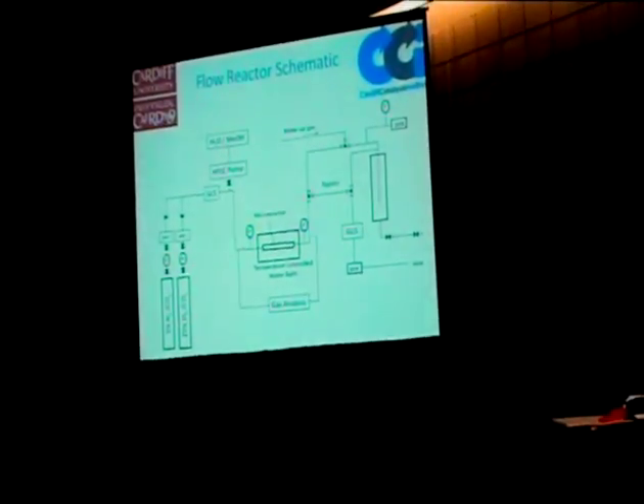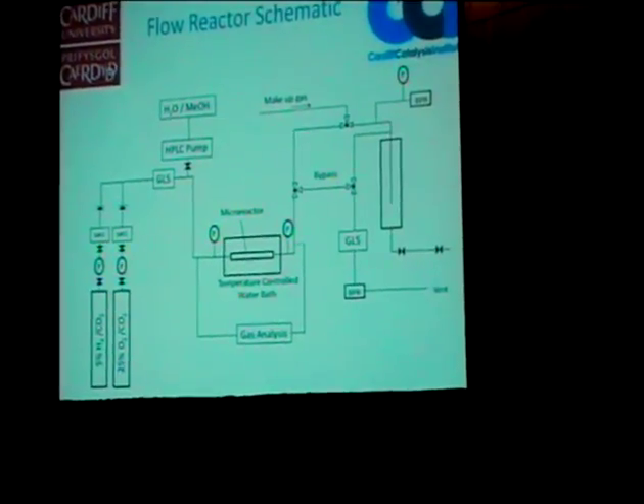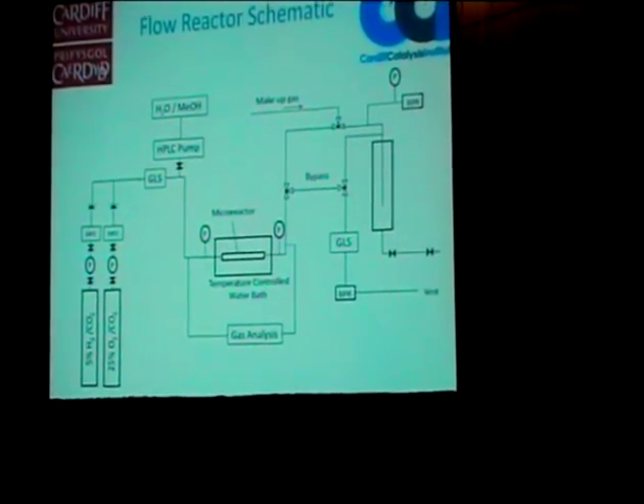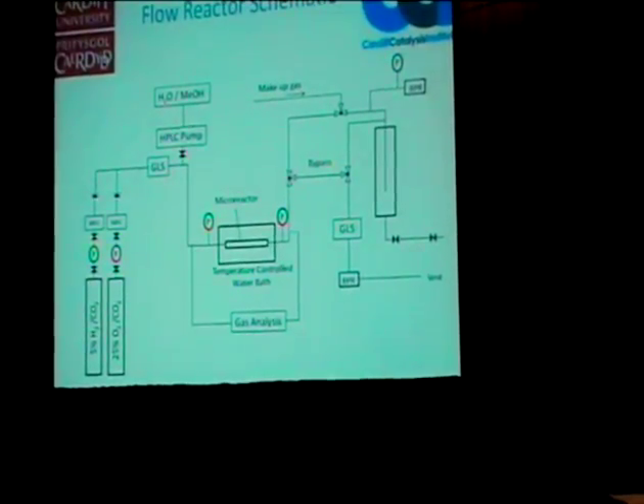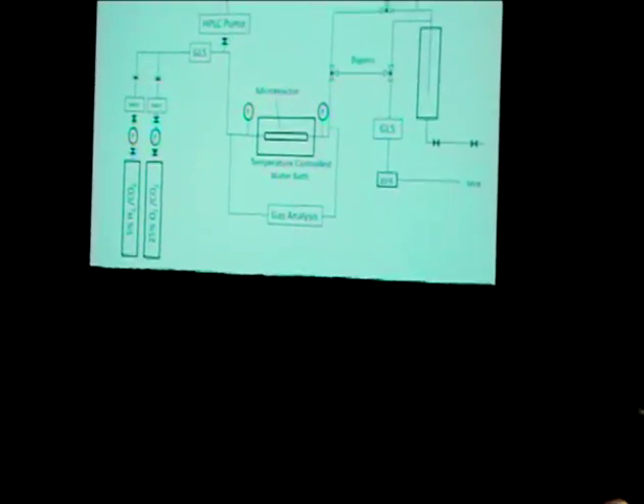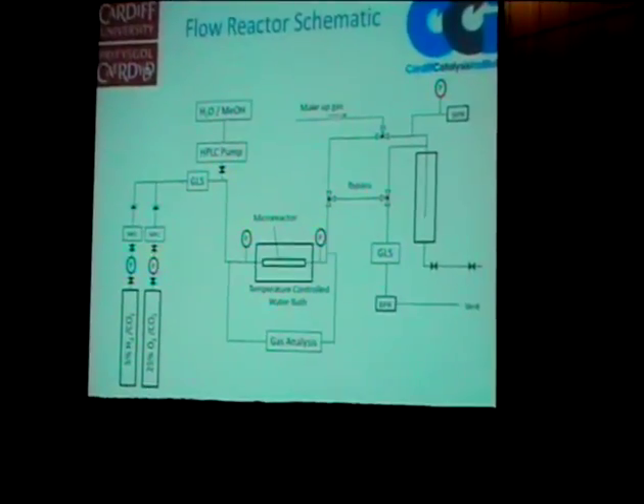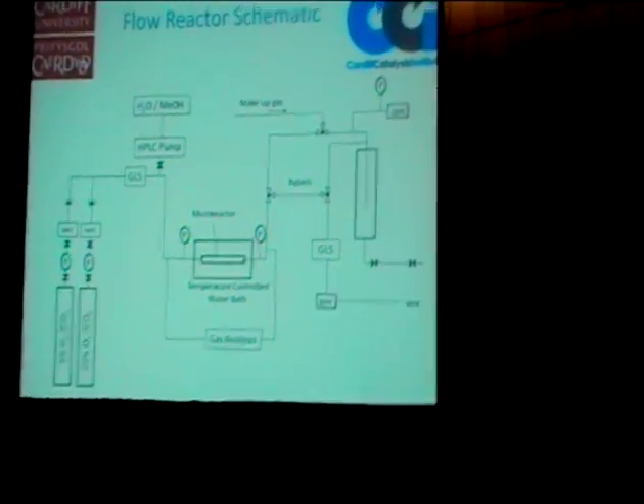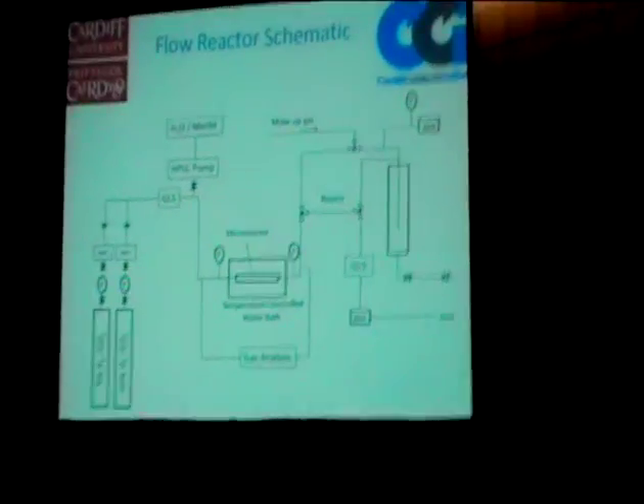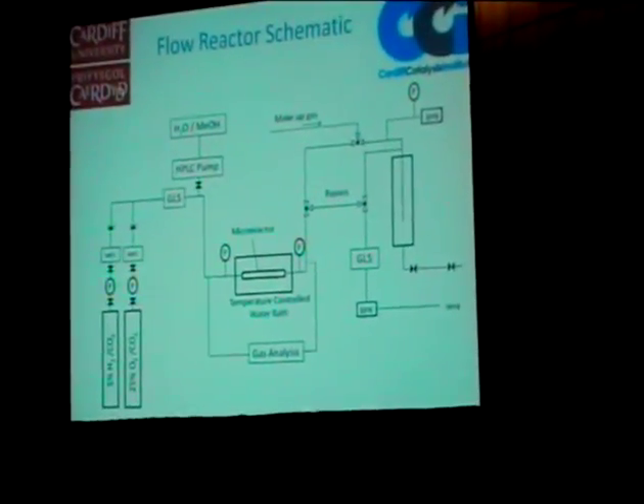So now we're passing our hydrogen and oxygen feeds, both diluted in CO2. This is one for safety reasons. Another benefit of using CO2 is that a small amount of CO2 will dissolve in the solvent, therefore acidifying the solvent slightly and stabilizing the peroxide. We use water and methanol as our liquid feed. We use the methanol to improve the solubility of the hydrogen and the oxygen in the solvent.